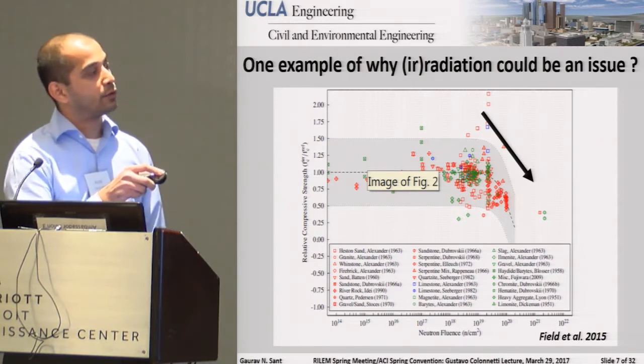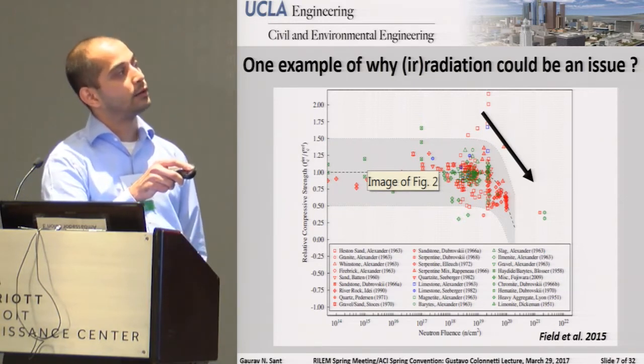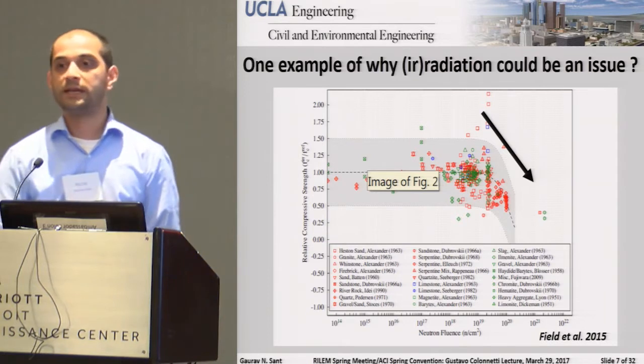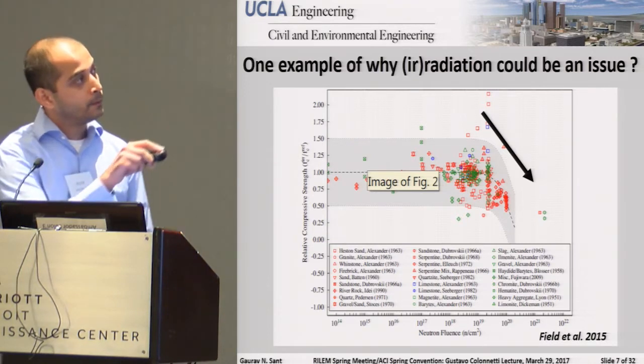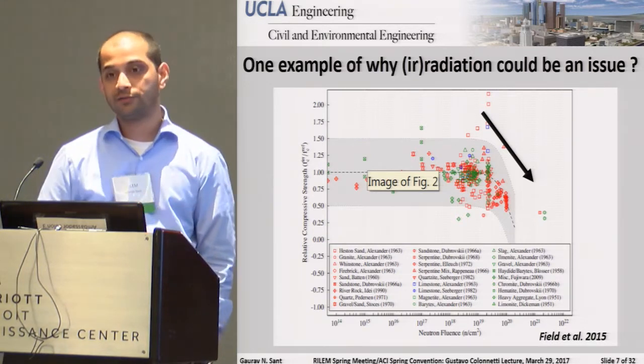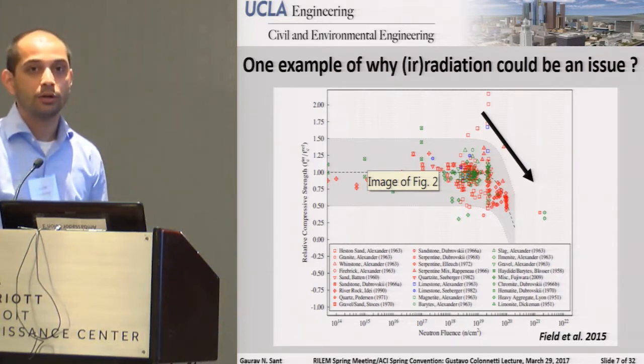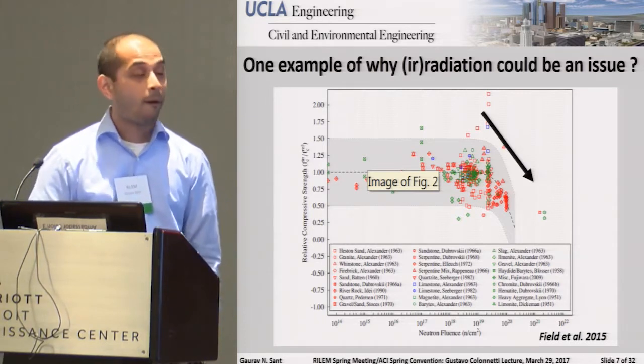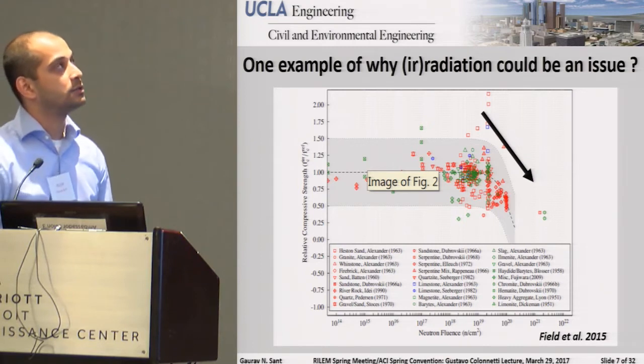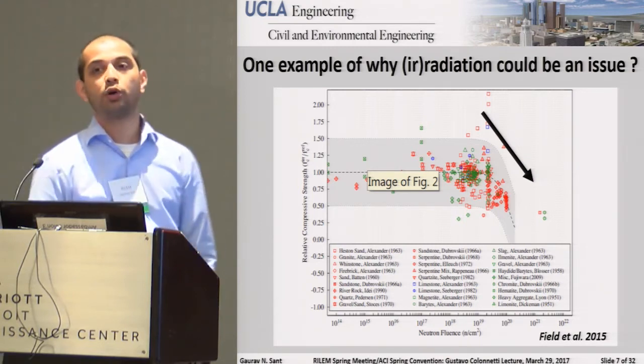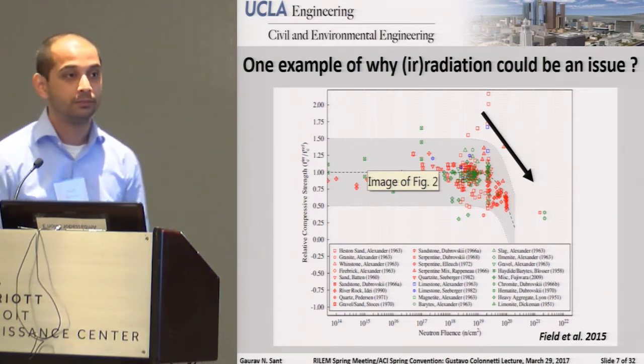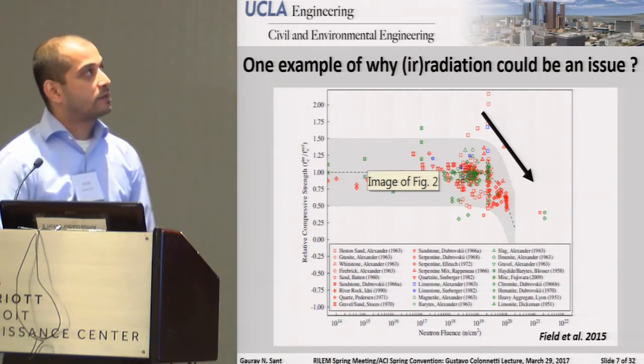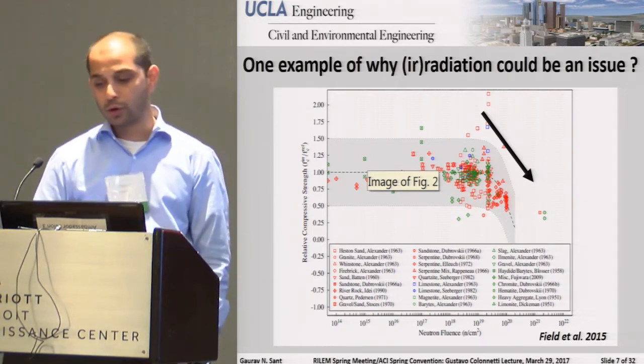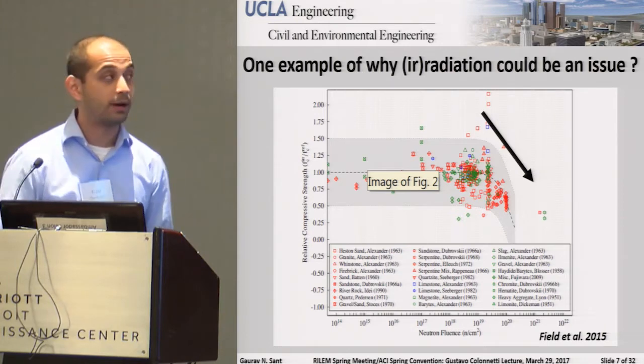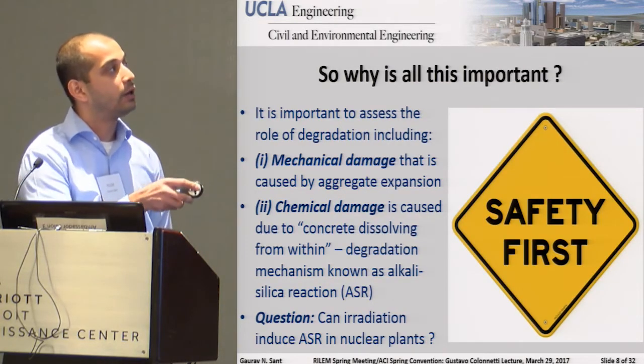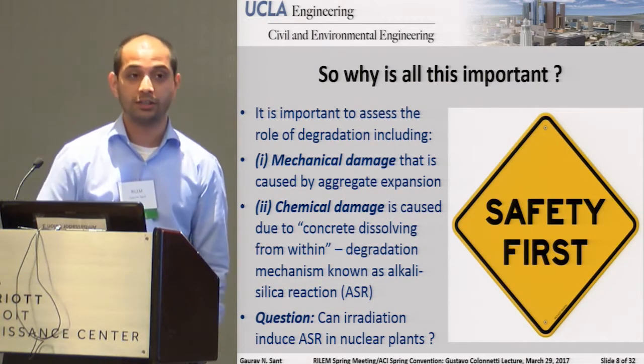If you look at the relative compressive strength, you see that up to a given point of neutron exposure, there's basically no change in the compressive strength. And then you see a really sharp fall off. Now, the question that becomes important in this context is, well, why? So looking at some of these things, it was determined that we should try to understand the effects of radiation. That being the case, there are two things I'd like to point out. Based upon work that has been done in the past, it's reasonably clear that you get mechanical damage following radiation exposure.